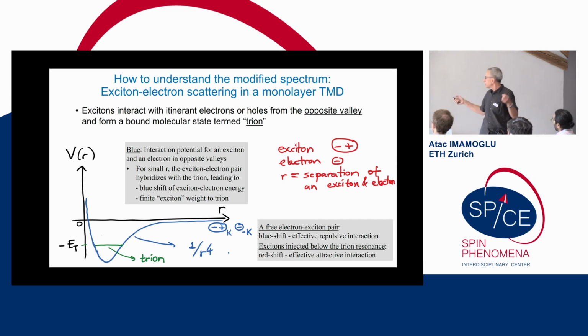That is, consider an exciton in the K valley and an electron in the minus K valley. The physics is interesting only if exciton and electron occupy different valleys, so we consider a scattering state consisting of these two. Their scattering potential supports a bound state, the so-called trion state. It's the analog of the H- molecule. The exciton can actually capture an electron and form a bound state with it. And this interaction potential is 1 over r to the 4, a charge interacting with a polarizable neutral object.